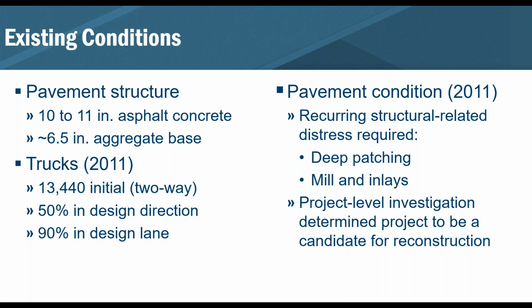All right, so some of the existing conditions: the pavement itself was about 10 to 11 inches of asphalt sitting on top of about 6.5 inches of an aggregate base. Back in 2011, there were about 13,000 trucks, both two-way, and looking at about 90% of the trucks in that design lane.